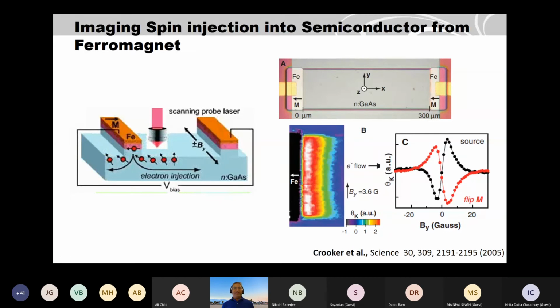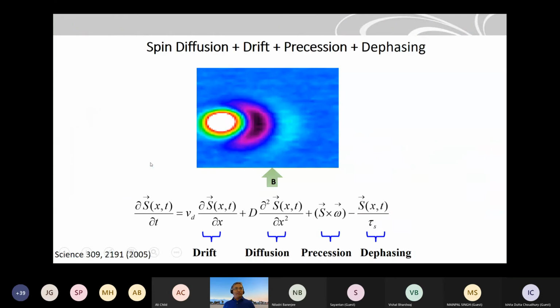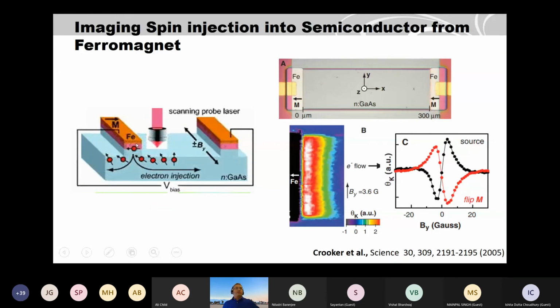Then moving forward, they tried to make some practical devices. So the practical devices is that they put these ferromagnets to inject, but the detection was not possible with the ferromagnet, but they could measure how spin was injected from the ferromagnet. So the previous experiment was all optical. You create spin polarization in semiconductor by optical means, also detect by optical means. But here, what you are doing is electrical spin injection from the ferromagnet into the gallium arsenide. So you apply a bias, so electrons from iron are getting injected into the semiconductor, and they are also diffusing here. So this is the real device picture, and here is the similar optical image they create.